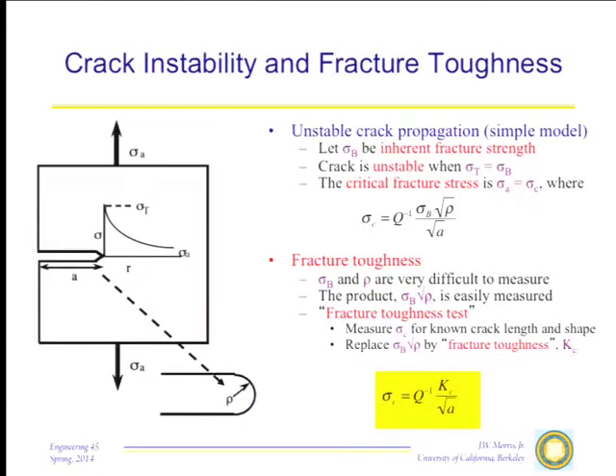Well, let's get to fracture toughness. How are we going to describe this? There are various complicated ways to do fracture mechanics. I've always liked the simplest one, and it's always worked very nicely, particularly when you start trying to design steels and such things that have fracture toughness. This is the most convenient way to look at it. Let's let sigma b be some inherent fracture strength, such that the material here at the crack tip is going to start breaking if the stress ever gets to sigma b. The crack will therefore become unstable when the crack tip stress sigma t is equal to sigma b.